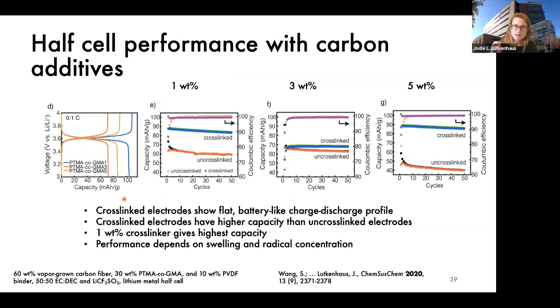Now you can see the dramatic effect of cross-linking when you build a battery with it and cycle it. In all cases, the cross-linked cell performed much better than the uncross-linked cell. This is because we've addressed these issues with the material's dissolution. We do have varied behavior, and we describe it more in the paper, but I think it's related to some interplay of swelling, because the 1 weight percent swells a lot and the 5 weight percent doesn't, and the radical concentration, because there is variation as we change the composition. So I'm not going to go into that.